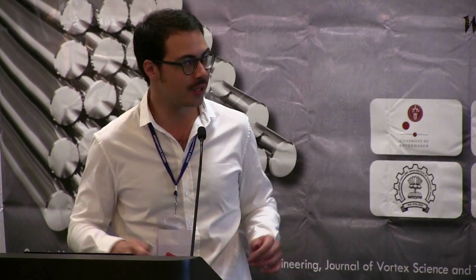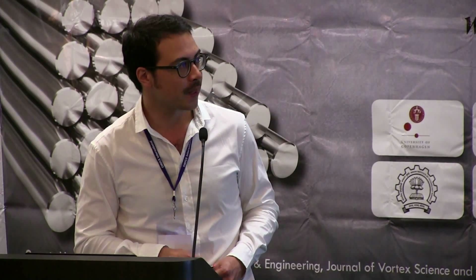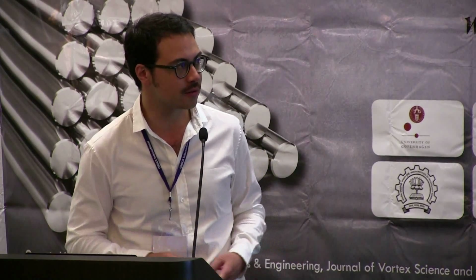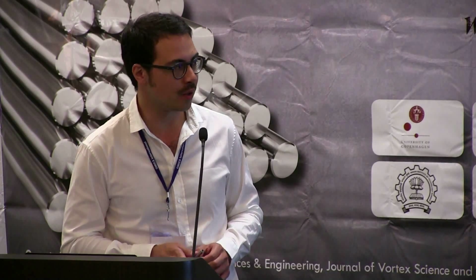And so now we come to the training process. We investigated the SIMT training, which means stress-induced martensitic transformation. So you have an SMA wire that is mechanically loaded permanently, and you are in the martensitic phase, and then you heat it up above the austenite finish temperature, AF, and it has the same load. It's stressed all the time, and after that you cool it down, and you repeat it for several cycles, maybe up to 100 cycles. It's what we were reading in the literature, and it was about 100 cycles.